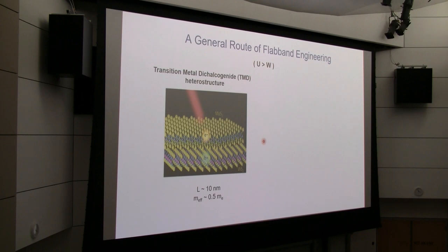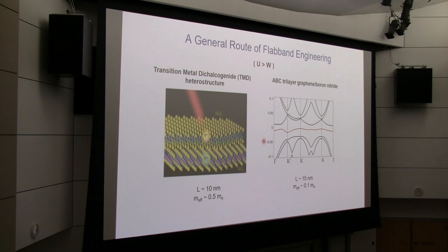So I will tell you two specific examples that we have explored quite a bit. One is using transition metal dichalcogenide. You can get a lattice on the order of 10 nanometer, and you have an effective mass of 0.5. So it's very strongly correlated. And I will also give you an example where you have a graphene boron nitride heterostructure where you can control a lot of relevant parameters, including band topology and bandwidth, in situ with the electric field.